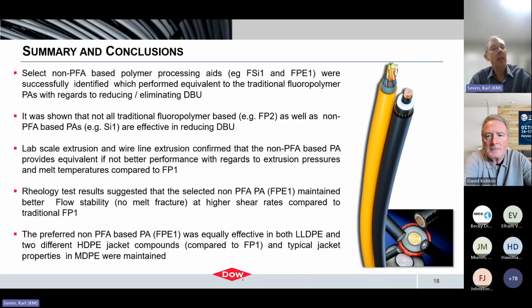Yeah, it's a good question. They're actually in a different range. The overall loadings of these processing aids that were looked at within this study that I'm presenting here are higher, but overall, as a percentage of the full formulation, it's still very low. The fluoropolymer processing aids are known to be effective at very low levels, 200 ppm, 100 ppm, 500 ppm. But a lot of processing aids, it's very common for those to get up into the 1% range, 0.5% range. So a little bit higher, but still overall percentage-wise, relatively low.